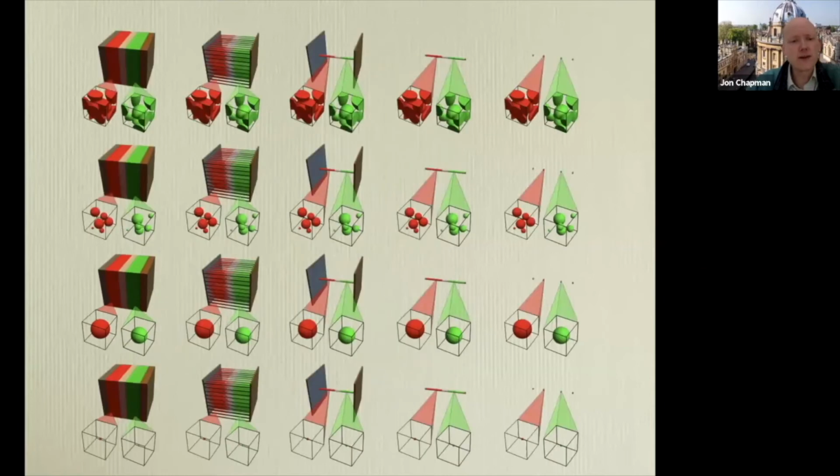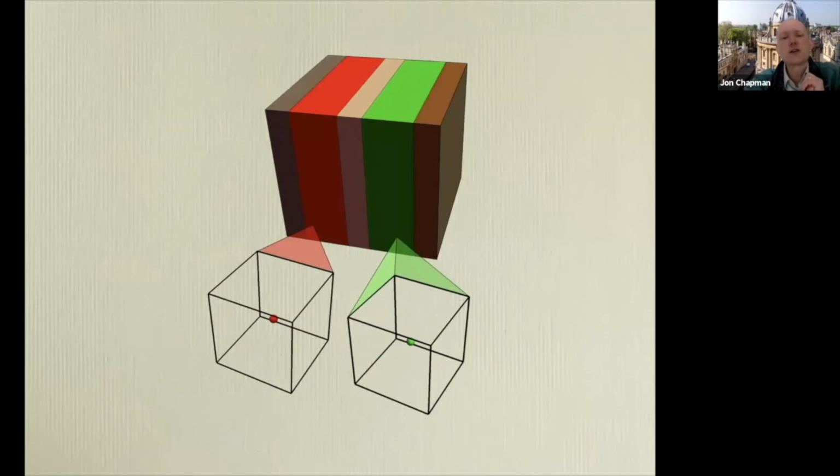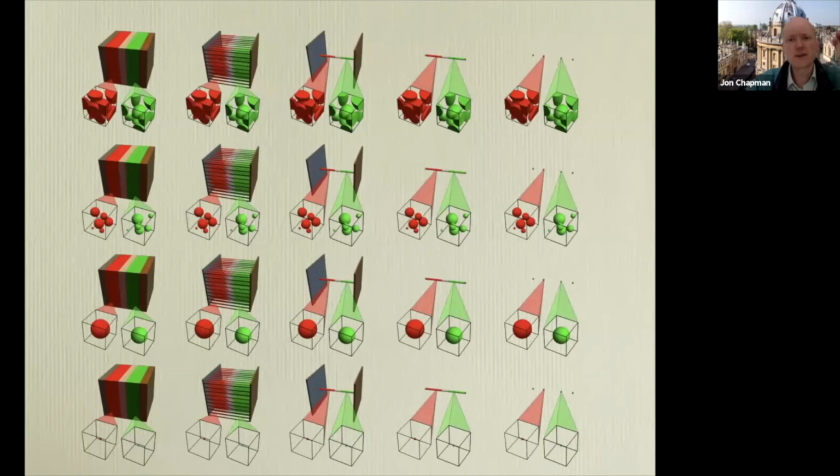And then the final thing you can do on this microscale simplification is to assume that the diffusion in the active material, the solid state diffusion, is much quicker than the timescale for discharge if you're discharging slowly. And then the concentration in the active material is uniform as well, and you just have an ordinary differential equation to solve. So I'm representing that by a point here. So that sort of explains how you get to this hierarchy.